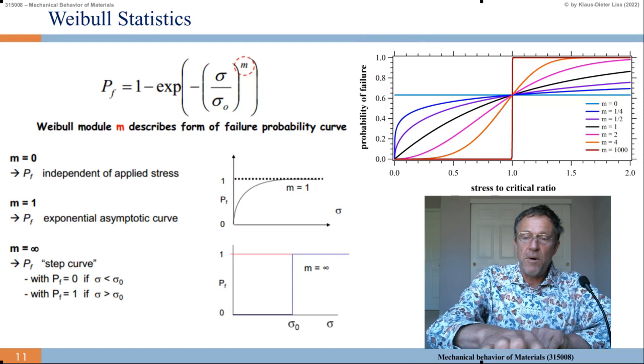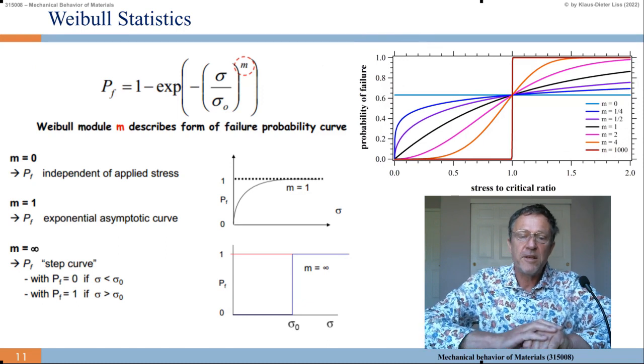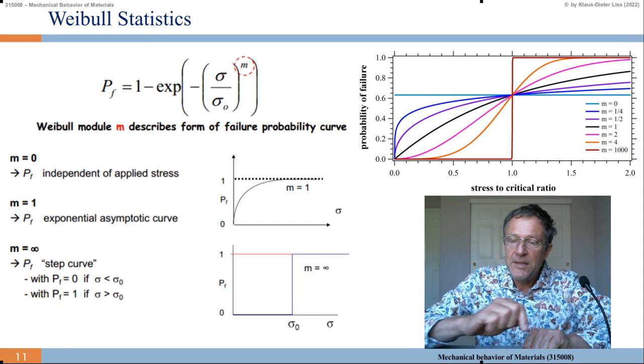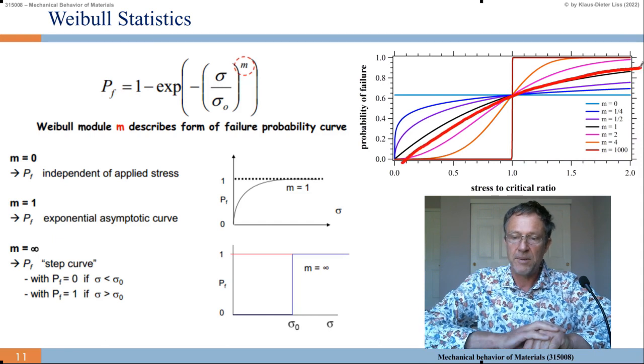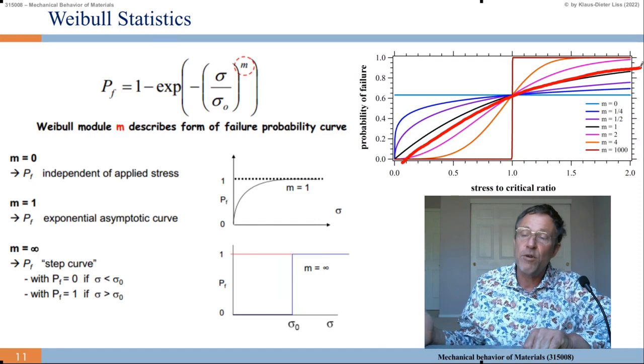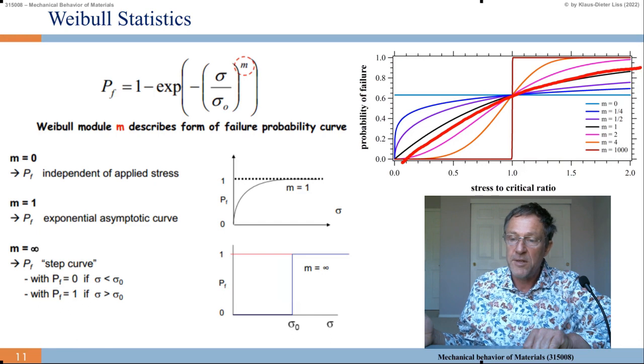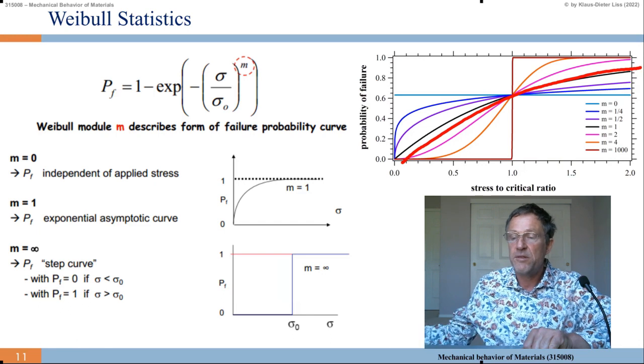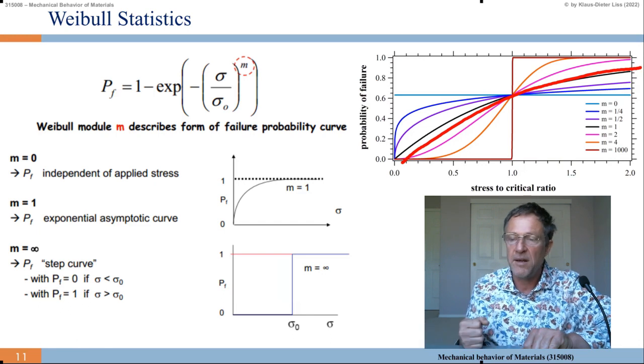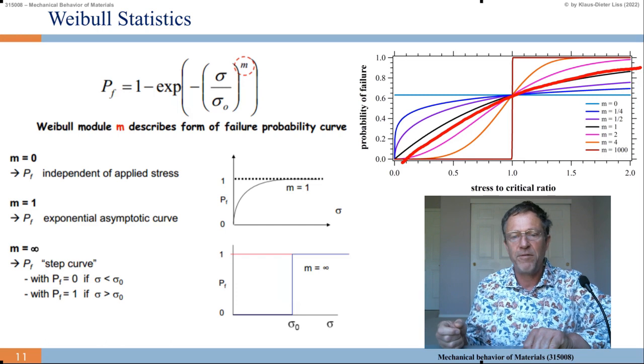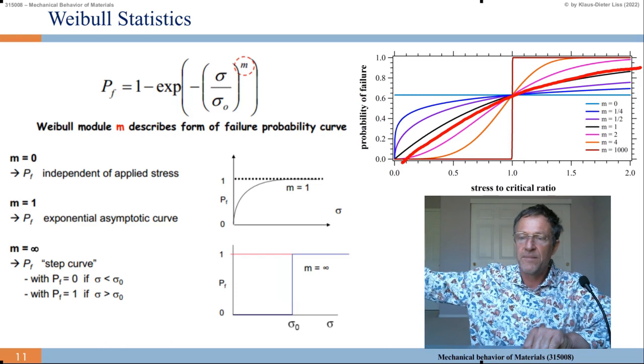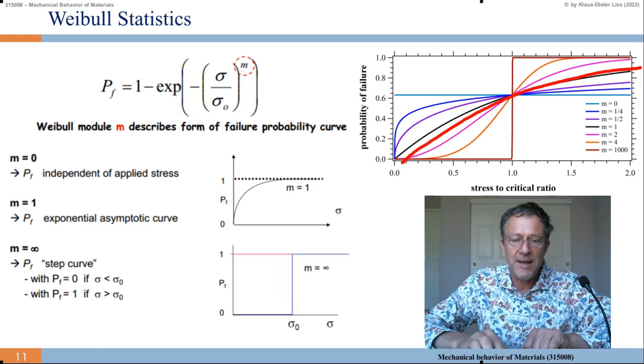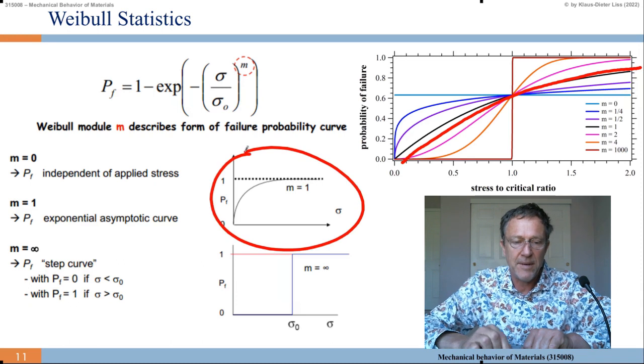If m equals 1, then we have a pure exponential, right? So m equals 1 is the black line here. It's just the exponential which goes up. If the stress is higher, the probability of failure exponentially goes up, asymptotic to 1. If I make the stress very high, I have 100% of failure, or very close to 100% of failure. Asymptotic to 1. Right, so we can understand that. This is shown here in that graph as well.